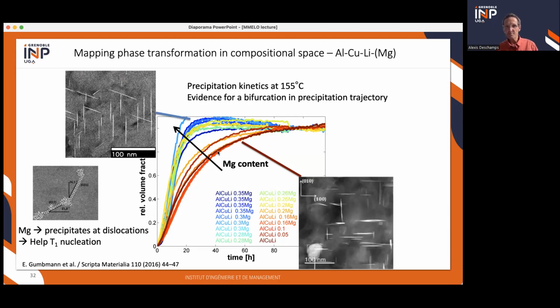And if you look with microscopy, not only do you have a change in kinetics, but you also have a change of precipitation trajectory. So for the slow kinetics, you're dominated by theta prime precipitates, and for the fast kinetics, you're dominated by T1s. And then we were able from this change of trajectory to understand that it was related to the formation of precipitates containing magnesium at these locations, which required a critical amount of magnesium.